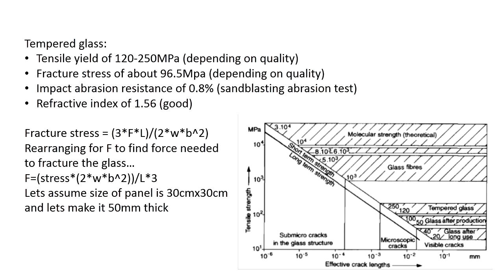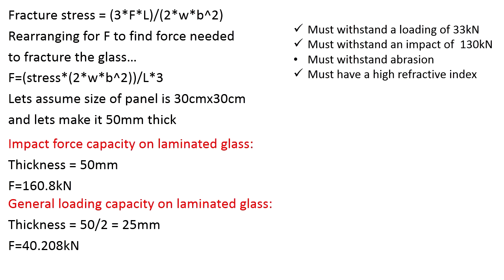By assuming the shape of the panel is square, that makes things a little bit less complex. So let's say the panels are 30 centimeters by 30 centimeters, and let's make them outrageously thick, let's say 50 millimeters, or about 2 inches. So one thing with laminated glass is for short-term loading, both panes act like one chunk of glass. But for long-term loading, you must only consider one single pane. So let's see, we have an impact capacity of 160 kilonewtons and a general loading capacity of 40 kilonewtons before fracture, which fits our design criteria with a small safety factor.